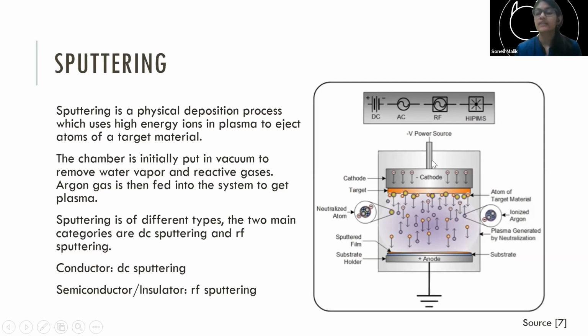Here, there is a magnet placed right below the cathode, which tries to confine electrons in this particular region, because you don't want a lot of electrons hitting your target, not just for the charge accumulation problem, but also because if high energy electrons hit your substrate, it could lead to re-evaporation of the material you deposited on the substrate. You don't want that. The problem of charge accumulation happens only for semiconductors and insulators, because for conductors, it will conduct off anyway. But even in this case, because of the magnets right where the cathode is, electrons are confined to a region close to the target.